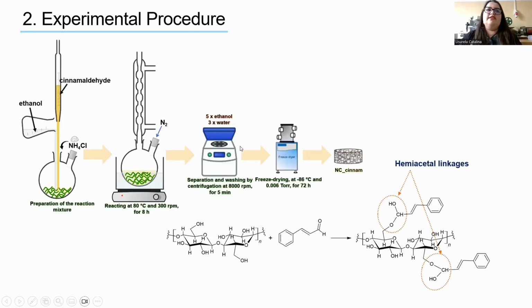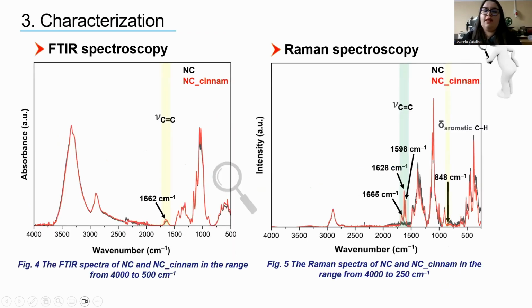Due to the promising results in terms of antibacterial and antifungal properties, we also attempted the chemical modification of nanocellulose with cinnamaldehyde. So we also attempted a covalent modification. This was conducted in ethanol under reflux. The chemical modification reaction is the one presented on the slide, where the hydroxyl groups of cellulose react with the aldehyde groups of cinnamaldehyde with the formation of hemiacetal linkages. Due to the overlapping of the absorption bands characteristic of cinnamaldehyde with those characteristic of nanocellulose, the FTIR spectroscopy was not very helpful in assessing if the chemical modification of nanocellulose with cinnamaldehyde took place successfully.